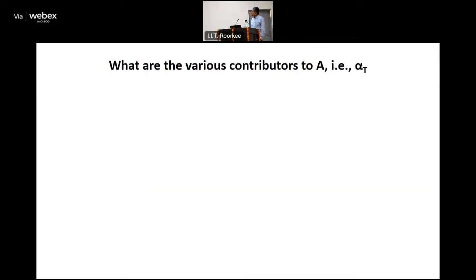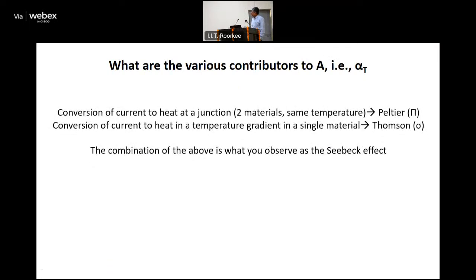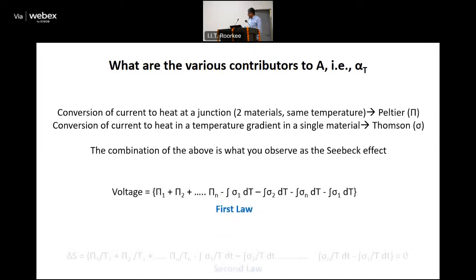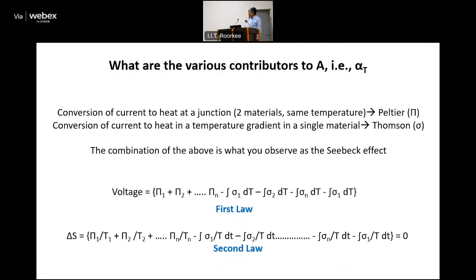So what are the various contributions to alpha? The conversion of current to heat at one junction at the same temperature is what we call the Peltier effect, and the conversion of current to heat in the temperature gradient in a single material is what later came to be called the Thomson effect. The combination of those is what you observe as the Seebeck EMF. So you just grind through this, it's not very difficult. The first law tells you the Peltier coefficients plus the sigma here, what we now call the Thomson coefficient. It gives you one equilibrium, and the entropy terms give you the other equilibrium.